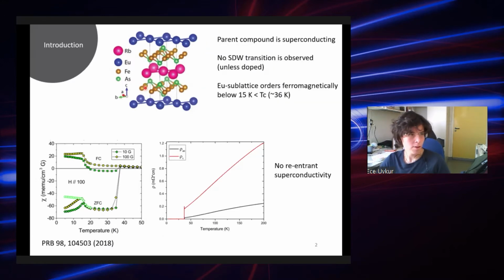Then let me start with just a brief introduction, as we heard about these systems quite a lot by now. The parent compound is superconducting with a transition temperature of 36 Kelvin, but there is no spin density wave transition observed like in the other iron pnictide superconductors, which is also surprising when we consider that this system is kind of two intertwined 1-2-2 systems. Well, this spin density wave transition actually appears when you start to dope these systems. But what is interesting is the europium sublattice that orders ferromagnetically below 15 Kelvin.